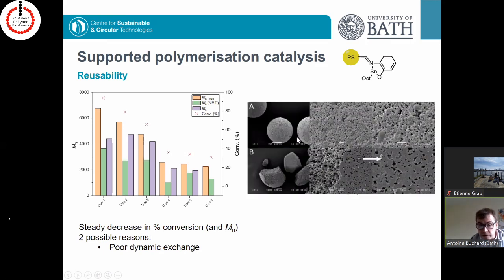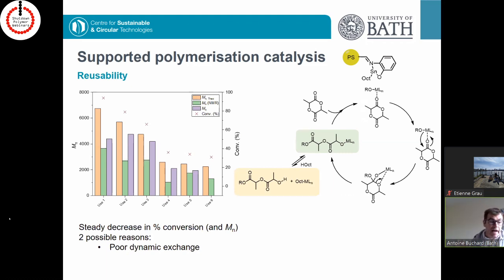And clearly, when you analyze the polystyrene beads by SEM, the first thing you notice, even when we crack them just to be able to see the difference between the core and the surface of these beads, is that before and after use, the surface is quite different. It looks like we've coated those beads in PLA a tiny bit, and that may explain the decrease in reactivity. And we may not be able to, in the end, remove completely the PLA which is stuck to the beads, because we may be stuck in this step of the catalytic cycle. So this relies on the dynamic exchange between the metal and the PLA growing chains.